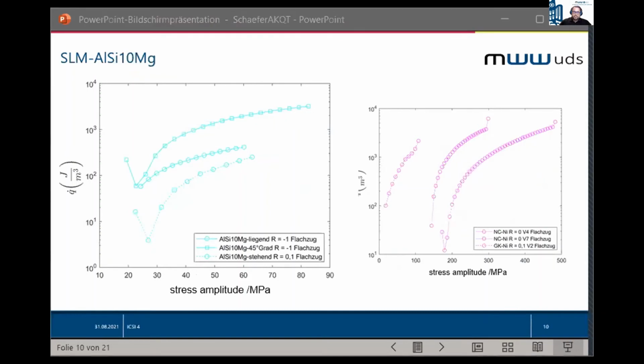We did this, and then we can contrast the heat generation to the step stress amplitude, and these curves here are gathered. Here you can see the results for aluminum cast alloy from selective laser melting, and of nanocrystalline and coarse grain nickel samples. And for the aluminum samples, there is no knee point visible. That means that the onset of plasticity leads to failure during less than 100,000 load cycles. This was the number of load cycles in one step. So we can evaluate the fatigue strength in only one easy load increase test, even without thermography. That's not surprising because it's a very brittle material.